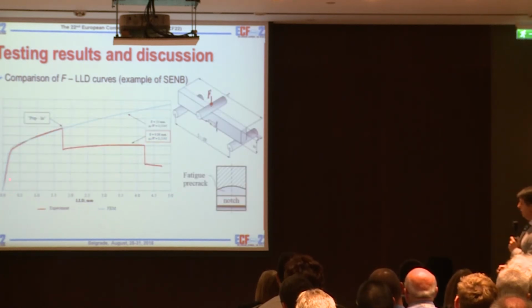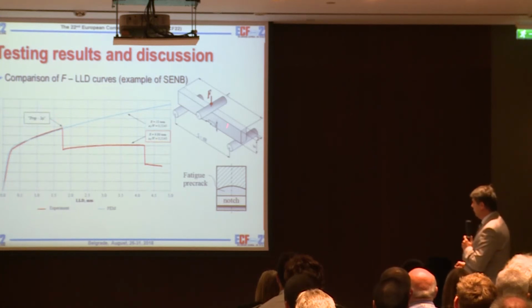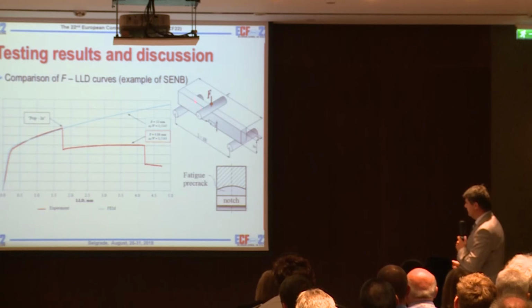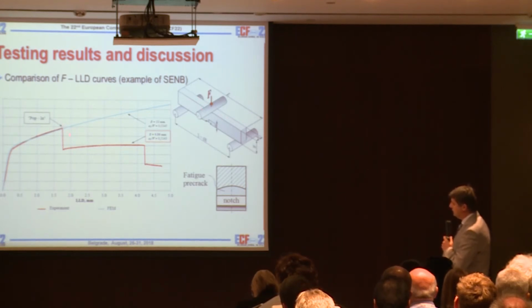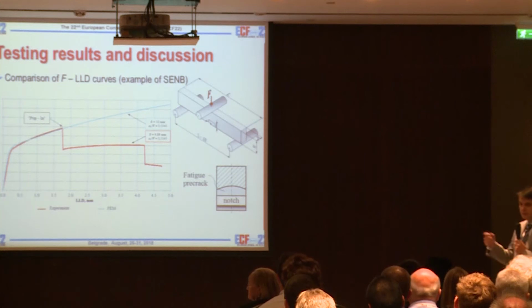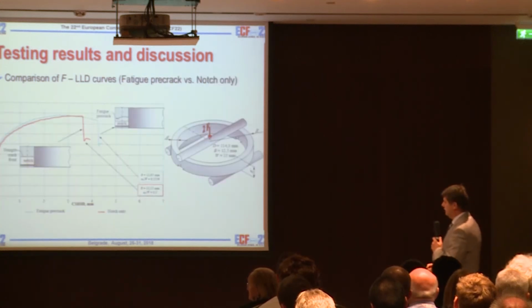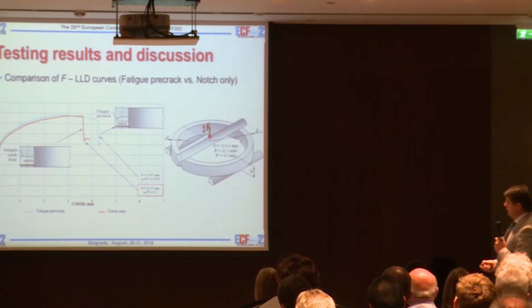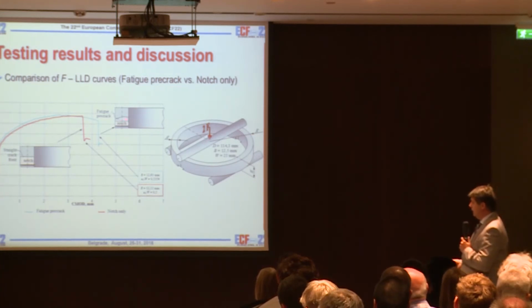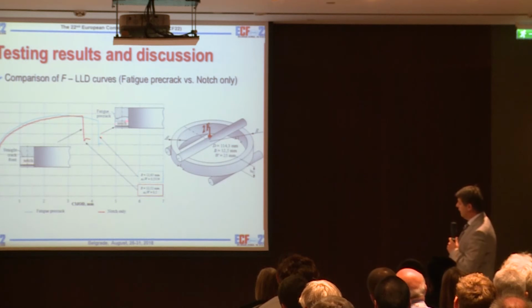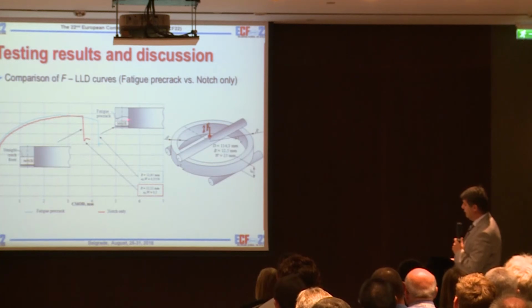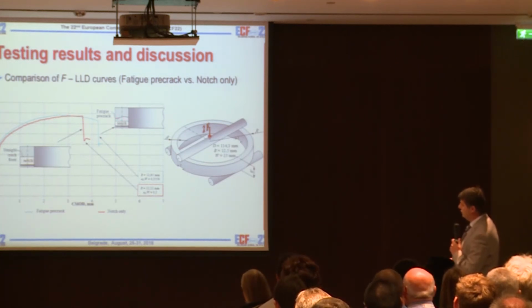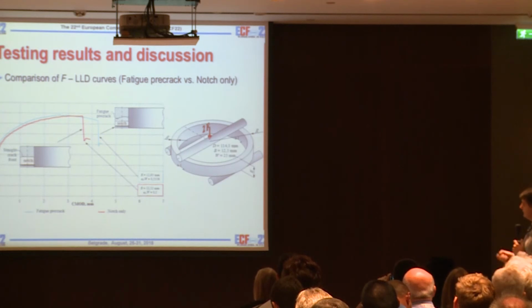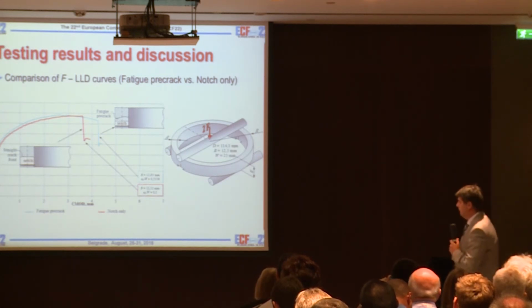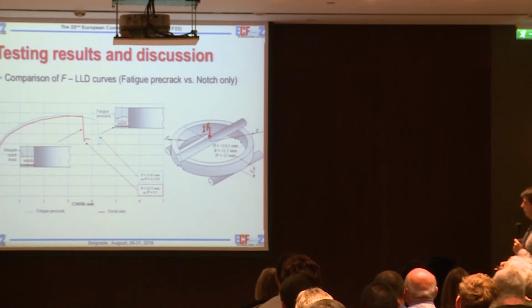Also, you can see the comparison for the base method made on the standard specimen. Also, we have here instability, so a quite good agreement. We use the same mesh elements and the same density of mesh elements too. So here we want to compare the notch and fatigue crack front. This is the blue line, and this is the average. So we can see that for the same average crack length, we get quite good agreement between these results. That means that it's really possible to use the notch specimen in this case for the testing.